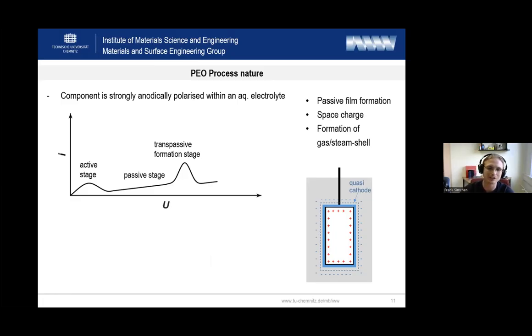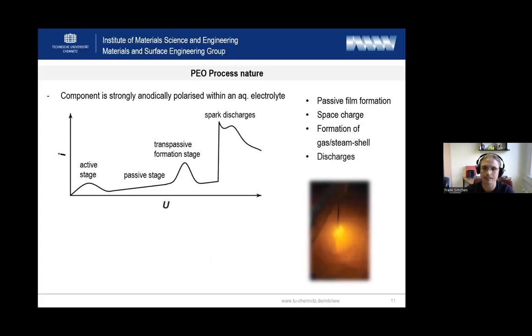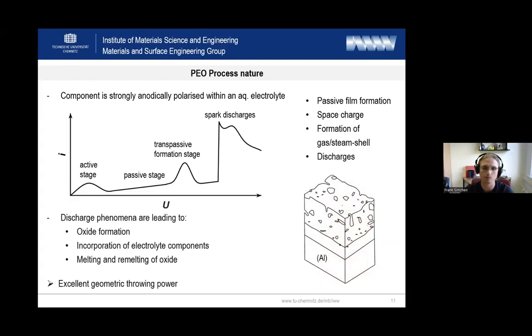And if we elevate the voltage more, the increasing space charge leads to the formation of a gaseous film which surrounds the working piece. And the interface between the gaseous zone around the working piece and the bulk electrolyte is getting an area of equal electrical potential, the so-called quasi-cathode. And afterwards, this quasi-cathode is the origin of plasma electrolytic spark discharges, which strike from the electrolyte into the substrate and form an oxide ceramic coating.